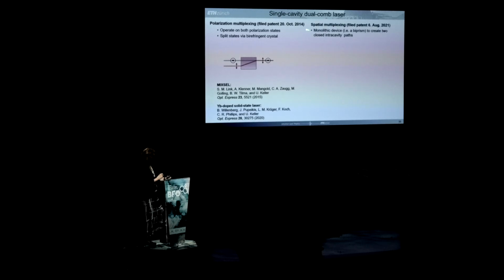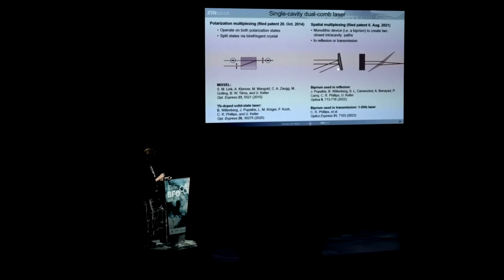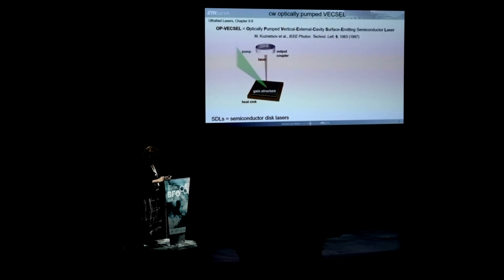Or we put in a spatial multiplexing. So instead of a flat mirror in the laser cavity, we put in a close to flat, but a little bit of a biprism, either in reflection or in transmission. And we change a little bit the path lengths inside the laser cavity. With this, we change the repetition rate by megahertz or kilohertz, and we get two mode-locked lasers out of it. Initially, we demonstrated that with an optically pumped semiconductor laser, because it's really simple, and that actually triggered this idea.